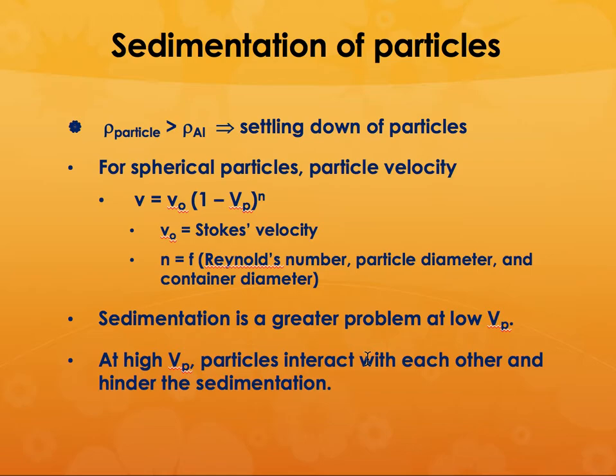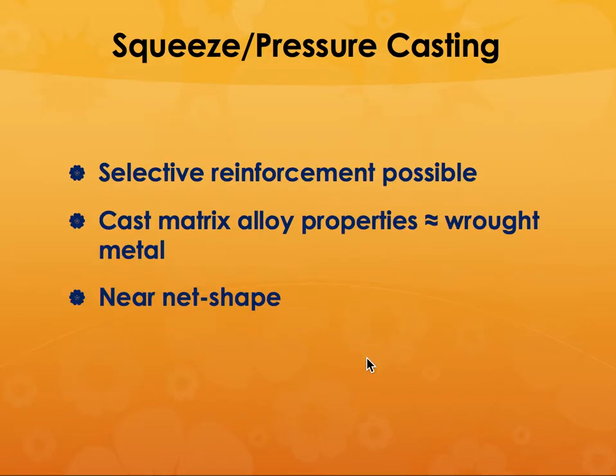So one of the issues with metal matrix composites, especially when you are using particles and things like that, is that those particles can have a density that is higher than that of the molten metal. So those particles can easily settle down. And the sedimentation is actually a greater problem at low volume fraction. And at higher particle content, the particles will interact with each other and hinder the sedimentation.